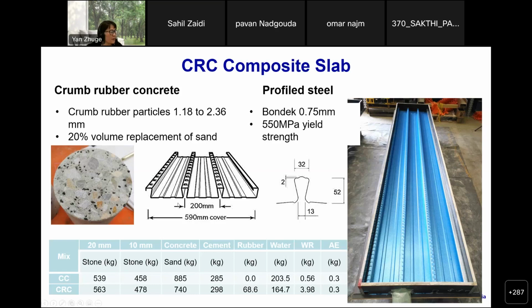So that is a profiled steel. We're using cold formed steel sections made by one steel manufacturer, with different sizes of profiles. And this is crumb rubber concrete. The particle size we used was from 1.18 to 2.36 mm for the rubber mix. And we have a 20% by volume replacement of sand, because previous material testing indicated that when the rubber content is more than 20%, it is not worthwhile. The profile tested was a bond deck with only 0.75 mm thickness, very thin, with 550 megapascals as the yield stress for the cold formed steel.